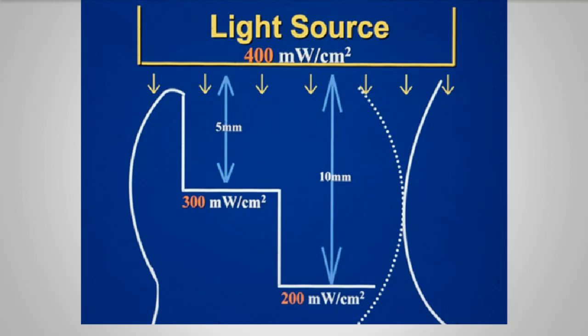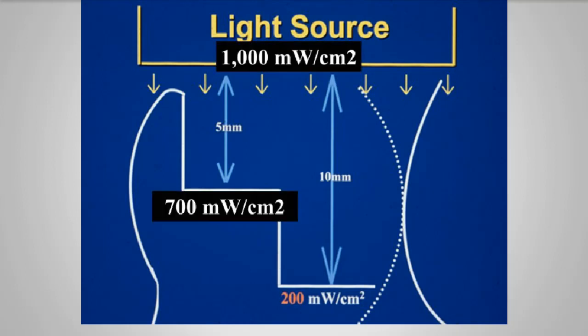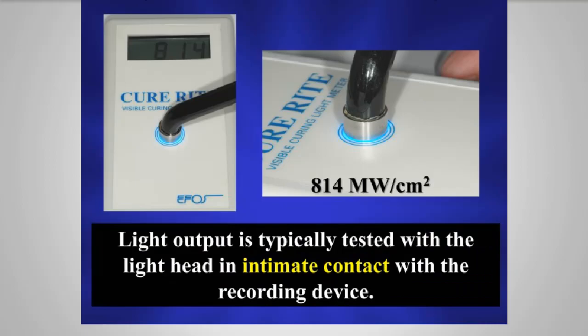Typically we test our lights with these little testing devices you see here, and I'm just going to show you very quickly. This is one I have in my office. This is just a light I happen to have. We tested it, and I got a reading of 814 milliwatts of energy, which is pretty good. What happens if I back off just 10 millimeters with that exact same light and retake that test? I go from 814 to 396 milliwatts of energy. So I'm losing more than 50% of that light energy traversing a 10 millimeter distance.